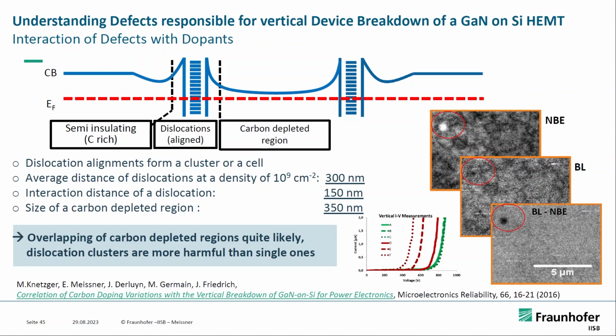Of course, there is some distance that they can travel - they cannot travel any distance they want. So if they are close enough, they are caught by the dislocation. And what you create in the insulating buffer, around the dislocations, is like an N-type conductive zone. And this is really causing leakage.